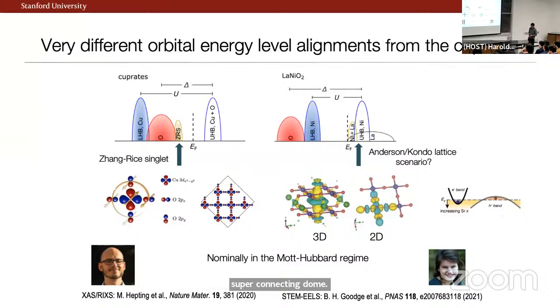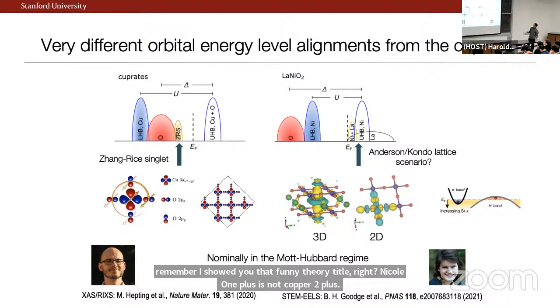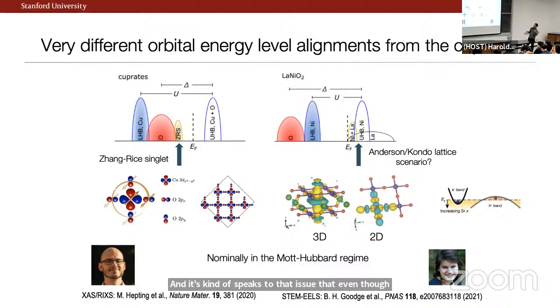This is a little bit of a jargon-filled slide, and so let me just focus on a few points. And some of this is for maybe the specialists in the audience, which is to say, again, our thinking was a lot about whether we can make an analogy to the high-temperature cuprate superconductors. And remember I showed you that funny theory title, right? Nickel 1+ is not copper 2+. And it kind of speaks to that issue that even though the starting ingredients, the orbitals, the electrons, and so forth are the same, we're at a very different kind of energy alignment. And so whereas in the cuprate problem, if I dope a hole in this antiferromagnetic insulator, you have this kind of very interesting situation where you have removed an electron with a lot of oxygen character.